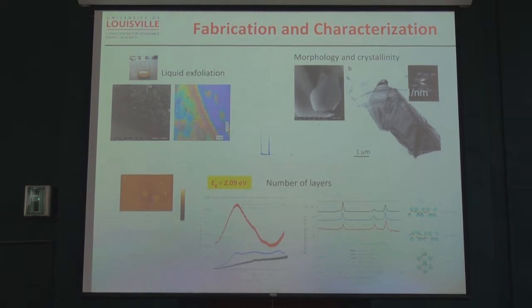So when you do this material, what we do is, I don't know whether you are familiar with centrifugation, right? When you put it in the centrifuge, only the heavy things deposit at the bottom. So when you take material from the bottom, you get many layers. This is the Raman spectroscopy for black phosphorus. When you take from the top, you get this. This means at the top you have mostly monolayers. In the middle, you get several layers because that's heavier, right? So it depends on where you pick after centrifugation.